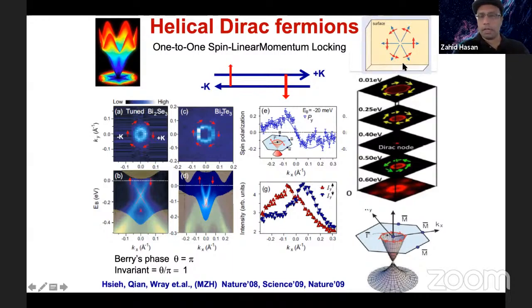And then you can also look at other surfaces, which is not always possible in all samples. Then you find that there is always an odd number of Dirac fermions, 1 or 3 or 5. In some surface in a particular material, or in some different materials, you can have additional surface states, but those additional surface states would come in pairs. And those states depend on the chemistry of that surface. So we sorted out all that stuff, and that's why you see that I'm summarizing three papers in a single slide. All those things have been sorted out and detailed in these three papers.